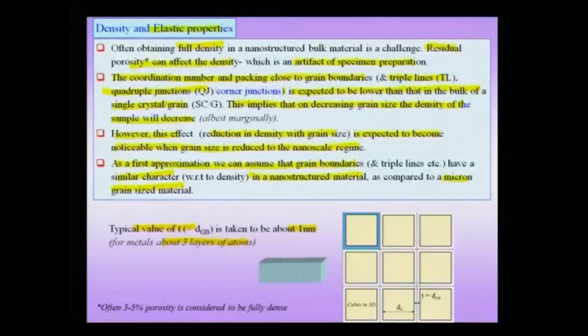Now, we had talked about porosity. We will be ignoring porosity in all these calculations, but as we pointed out, in some materials, so-called bulk or fully dense material as reported in literature could actually have about 3 to 5% porosity. And this 3 to 5% porosity would actually dominate over some of the effects we will be talking about regarding grain boundaries and triple lines, but nevertheless we will assume for now that it is absolutely theoretically dense except for the grain boundary and triple lines, etc., and there is no contribution of porosity to the overall effect of reduction in density, or therefore its influence on elastic properties.